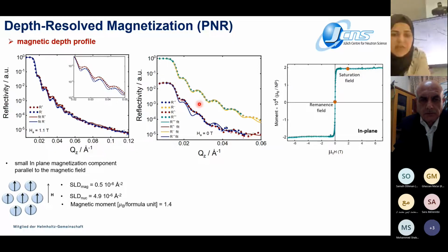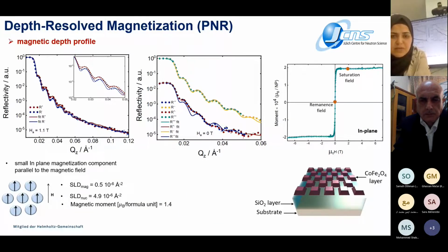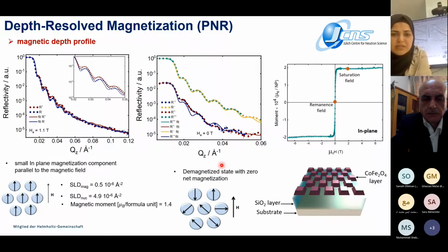We fitted the data, assuming zero, and it ends up with zero magnetic SLD, which is not a surprising thing because, as we can see in the magnetization versus field, the sample did not show any remanence at zero field. But we can see here also that the model that we assumed to fit does not reproduce the data very well. It seems that we have some magnetic contribution coming in, as the fitting does not reproduce the data very well. So in the end, at remanence our sample is in a demagnetized state with zero net magnetization.